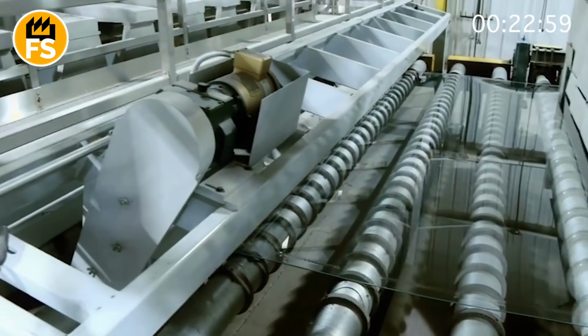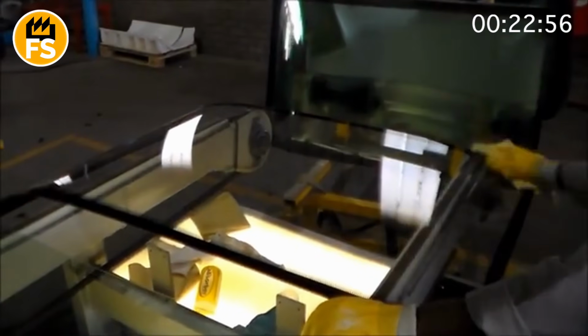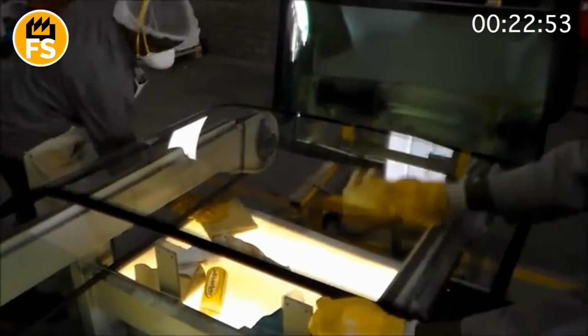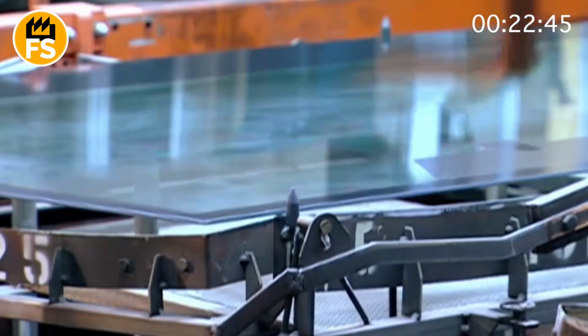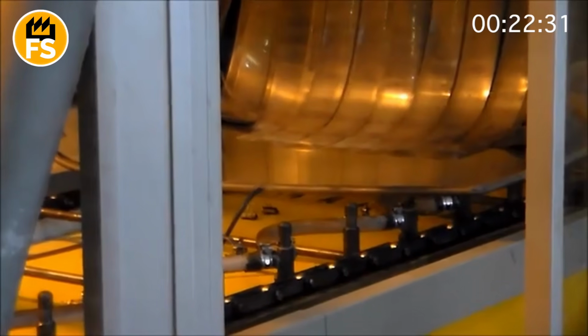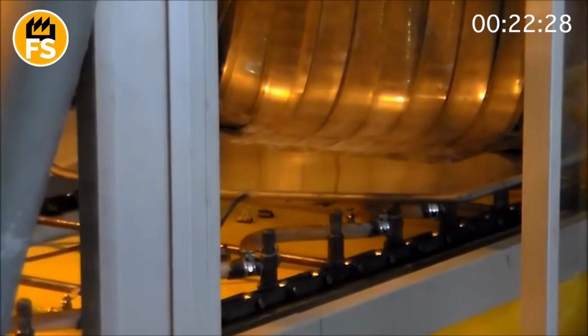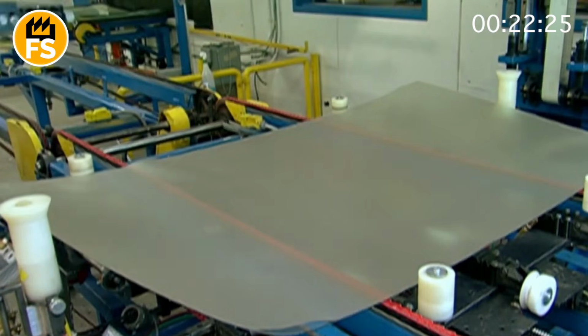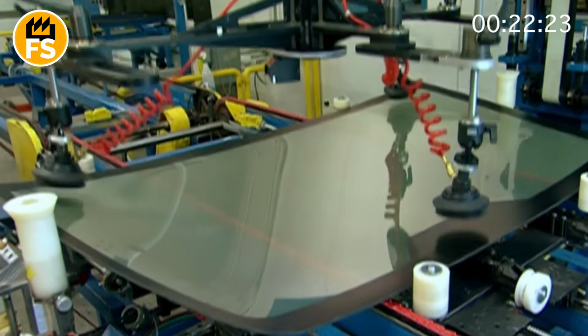After that, for the windshield, a triplex construction is used, which is a combination of glass and polymer film. Its fabrication involves several steps. Layer bonding. A polymer film is placed between two sheets of glass. The construction is placed into a vacuum press to remove air bubbles. Then the glass is heated in an autoclave to 284 degrees Fahrenheit under high pressure, ensuring a strong bond between the layers. Triplex has high impact resistance, and if damaged, the fragments stay attached to the polymer film, thus providing safety for the driver and passengers. Afterward, to enhance the properties of automobile glass, various coatings are applied.